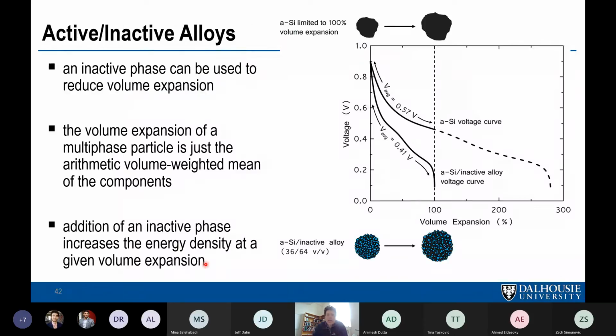But any time you have a material, even if you start with pure amorphous silicon, just limiting the voltage, you always end up with a high average voltage. If you want to limit your cutoff so that you end up with 100% volume expansion, you're just cycling the top part of the silicon voltage curve. You could do much better if you add an inactive component and basically dilute the silicon such that if you fully lithiate the silicon, then this particle overall will have 100% volume expansion. Then you're using the whole voltage curve of silicon and your average voltage is lower, and that'll give you a higher energy density. So if you are cycling at a fixed volume expansion target, adding an inactive phase increases the energy density because it reduces the average voltage.